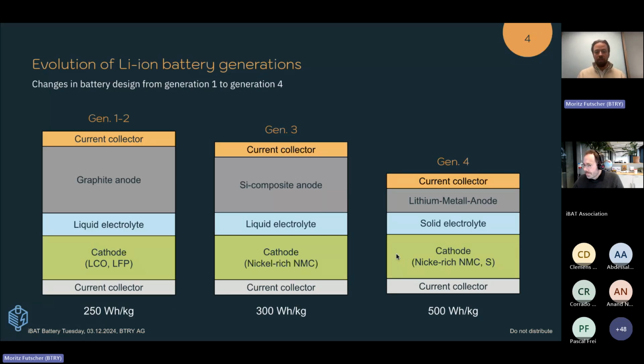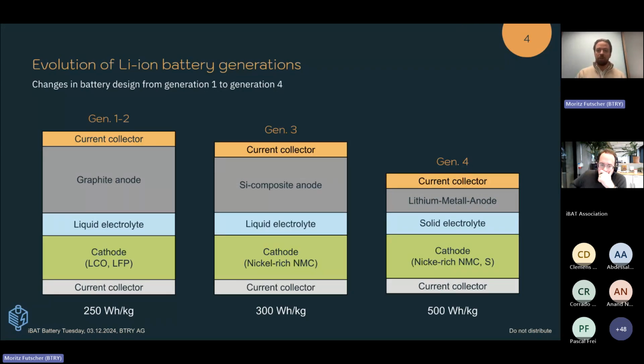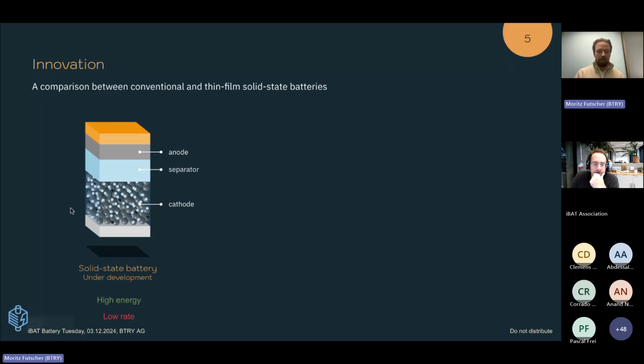But one thing really remained very similar throughout the years, and this is the structure of the battery. So all of these layers, for example the cathode, are typically in the order of 100 micrometers in thickness. And the thickness of the cathode is one of the aspects which really limits the rate performance of these devices. And here you can again see this in a different schematic way, where you have a solid-state battery, where you see the cathode is actually not a pure material. This is, of course, a composite material with the active particles, but also some additives for conductivity. And this is under development, but as mentioned, these are rather thick layers still, which limits the rate performance.